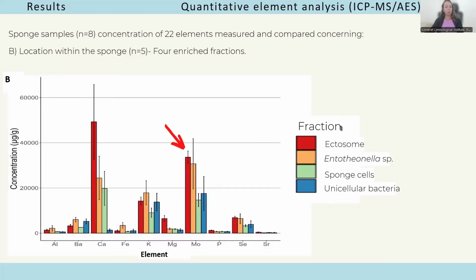The ectosome suggests that molybdenum-rich material may accumulate near or on the outer sponge layer. The Entotheonella fractions suggest that a specific symbiotic bacterium may also be involved. I also want to draw your attention to calcium in the ectosome. This becomes relevant in the next slide, where we look at spherical structures containing both molybdenum and calcium.